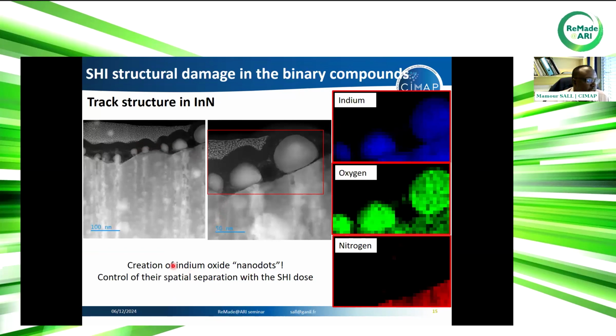This is again visible here. So we have many tracks in indium nitride. On top of each track, we have this hillock of different size. Once again, there is no nitrogen in the hillocks, but only indium, which is oxidized after putting the sample in air. So by the way, this is a way for creating indium oxide nanodots by using swift heavy ion irradiation. We can control the spatial separation of these nanodots. We can also control their size by playing on the swift heavy ion irradiation.